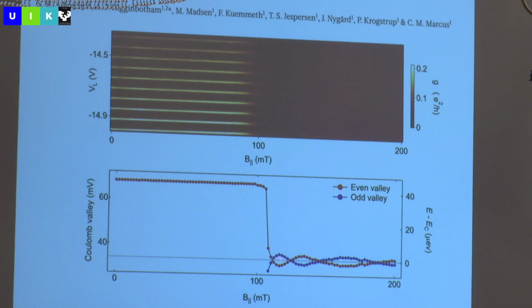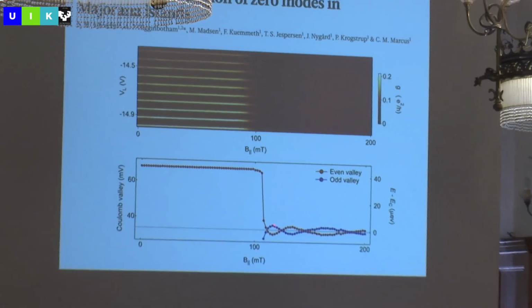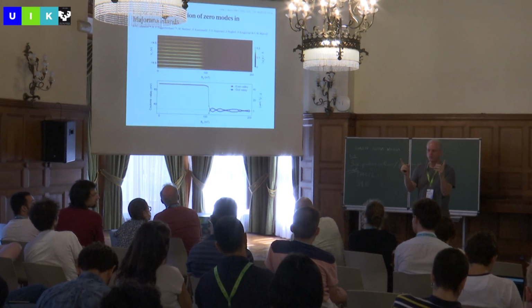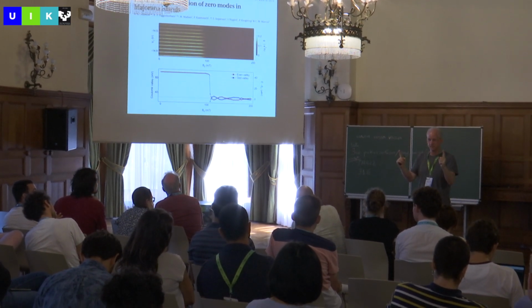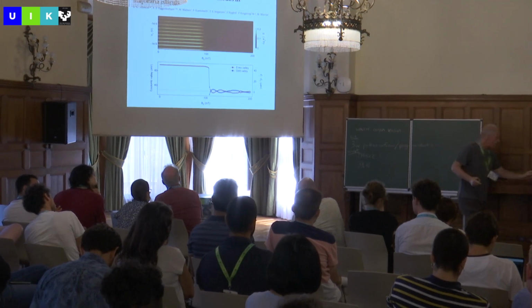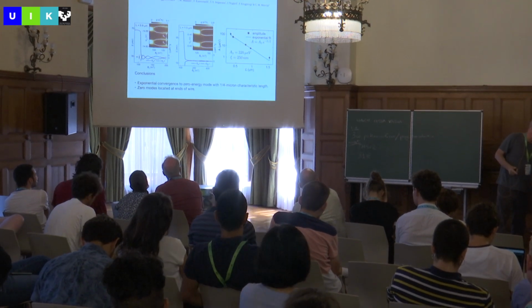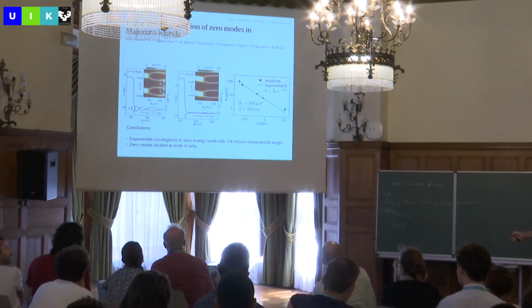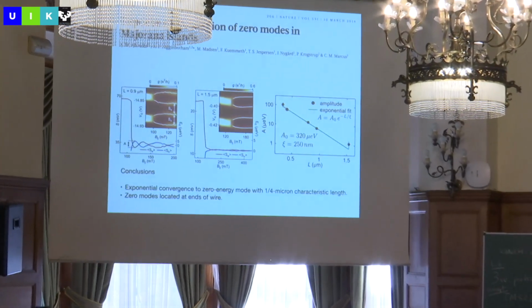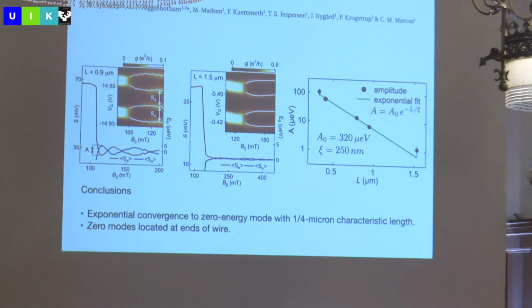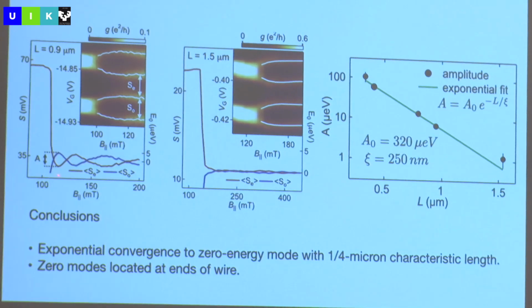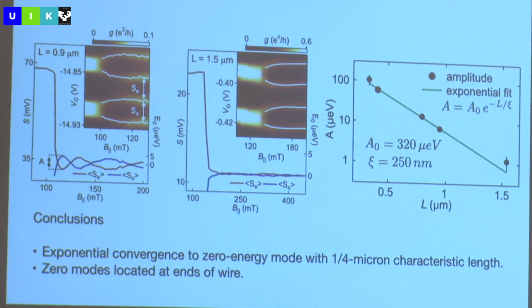And the oscillation amplitude, well, what does theory predict? Theory predicts that some measure of this oscillation amplitude should tell us how long the wire is. Because as the wire got longer, they should really become at zero energy. So then we have a harder job, which is to do the experiment a whole bunch of times with different length wires and see whether the amplitude of that oscillation, what I called A, actually falls off exponentially.